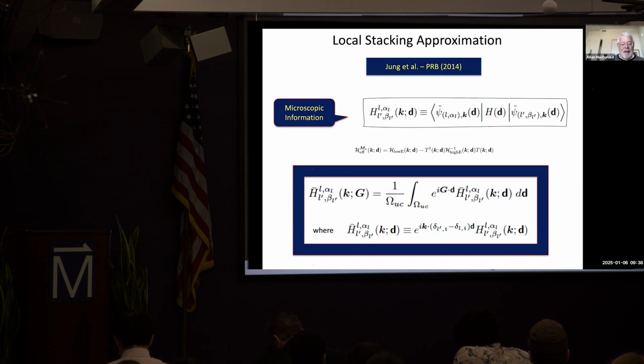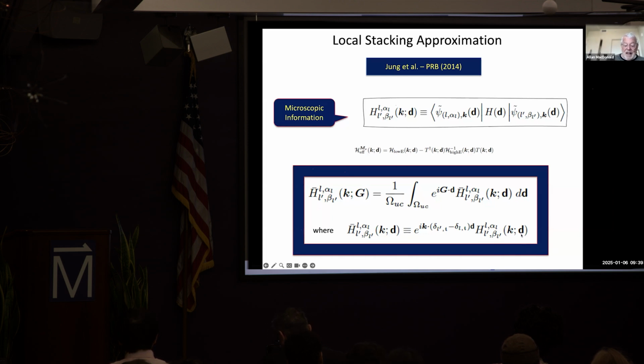And that is that, if I actually construct this Wannier function and representation the way I described for every displacement d, then if I translate, let's say, the top layer of a bilayer by a lattice constant, then just the way I'm labeling the Wannier functions, the system really returns to itself, but what I consider to be R equals 0 in one of the layers changes when I change D by a lattice constant.